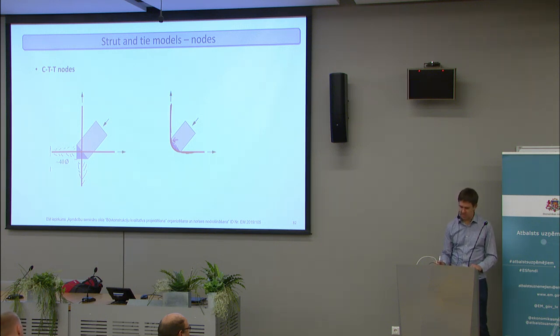And what we also must have here is a bar through the bend. It's also required in Eurocode to have a bar with the same diameter as the bent bar that goes through the bend, which is to redistribute the stresses from the top. It's like this. It's to prevent this expansion here, and basically cracks like this, due to compression right inside the bend.